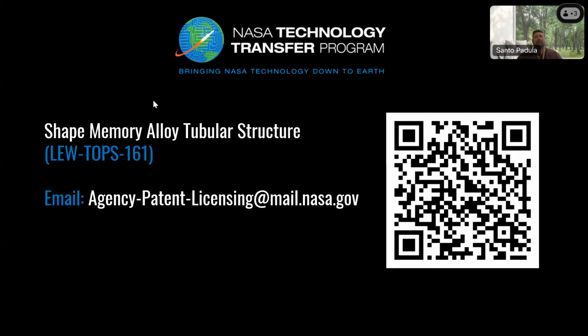We are currently pushing to new alloys and processings that promise to extend that up into the 10 to the power 7, 10 to the power 8 range. So these materials now, like everything though, if we drive these materials within the structure trying to get every little inch of reversible strain in the system out of it, we can impact that and see lower lives, so higher debit on margin. But if designed properly, these can adequately perform the same numbers of cycles as conventional systems.